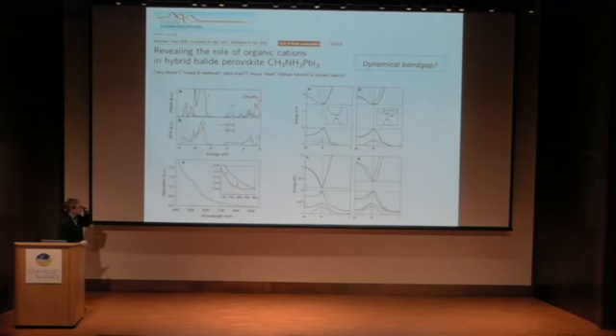So you might say, okay, is that coupled to the electronic framework or the electronic band structure, which might have some more implications for the photovoltaic properties? And there's been a number of suggestions that that's in fact true. In particular, I just picked out this one paper here, where they found that there was a strong correlation between the molecule orientation and the band structure, and indeed the band gap in this material. This is just a plot here showing calculations they've done for several different orientations.